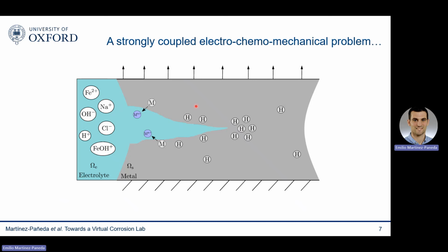In the interface between the metal and the electrolyte, you have chemical reactions, which might include material dissolution, the formation of a passive layer, the absorption of deleterious species such as hydrogen. Then these hydrogen atoms move within the metal, which is deforming elastoplastically due to mechanical loading, which is also rupturing the repassivation layer, and so on and so on. So there are a lot of things happening, all of them important, and all of them strongly coupled.